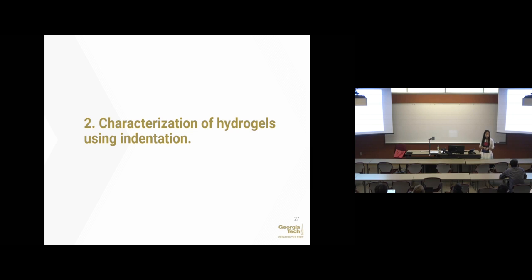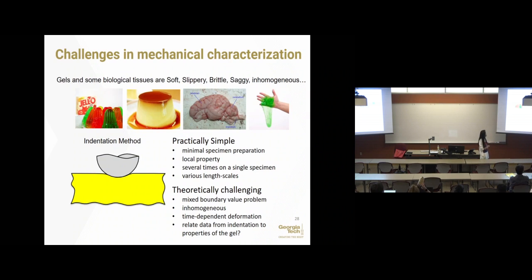Beyond this modeling, in order to get a quantitative characterization of the model, we need to characterize the material accurately. And because of this coupled deformation and diffusion, we need to rethink the traditional material characterization. We need to characterize both mechanical and transport properties in the material. Also, mechanical characterization of soft material is very challenging. I gave several examples of materials we are familiar with, just to give you some physical feeling. Most of them are very soft and slippery, and some of them are saggy. It's very difficult to do conventional tensile testing, compression, and torsion.